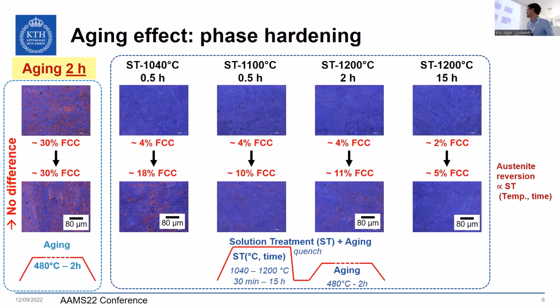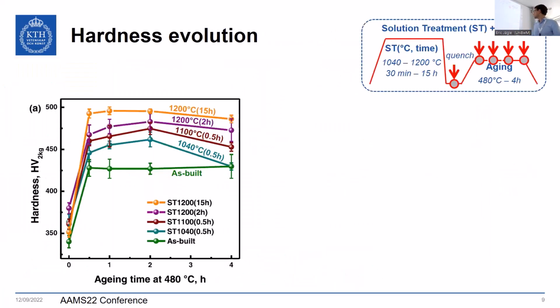FCC after aging. So this austenite reversion, this metastable alpha BCC phase transforming to FCC, is reducing with the solution treatment, which means that we have a more homogenized microstructure after higher solution treatment, which is expected, right? But what is really interesting is that with this process, we can tune the amount of FCC. We have the soft phases, and then we can tune the ratio between soft and hard phases that we will have in our materials, and then likely tune the mechanical properties, which is not possible in a conventional process because we don't start from this very heterogeneous microstructure.